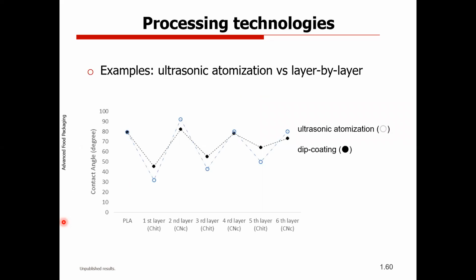Here I show you some results comparing the ultrasonic atomization and the layer by layer technology. What we tried here was to make the functionalization of polylactic acid films with different layers of chitosan and cellulose nanocrystals. So we saw that it's possible to compare based on contact angle for sure, and we are trying to address this with other technologies. We are able to build these different layers. Different contact angles are considered different surface materials.